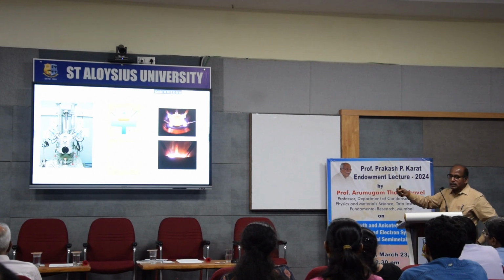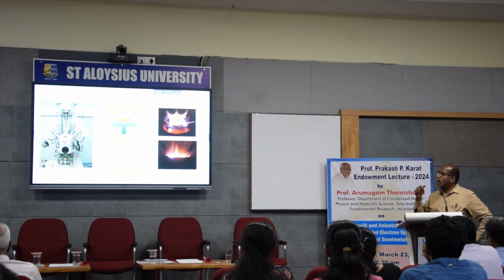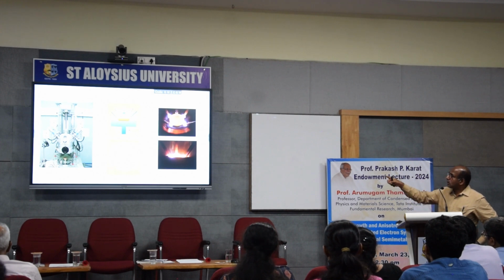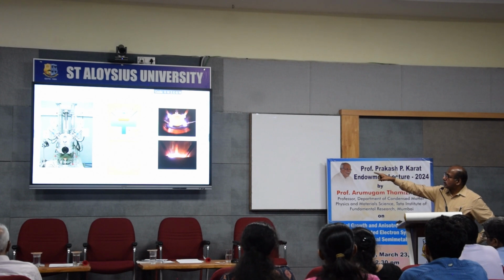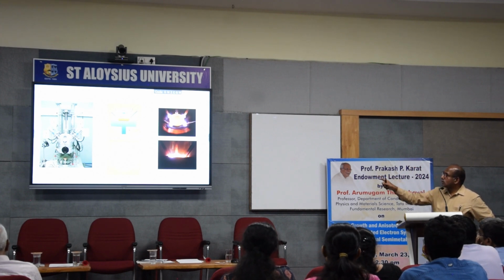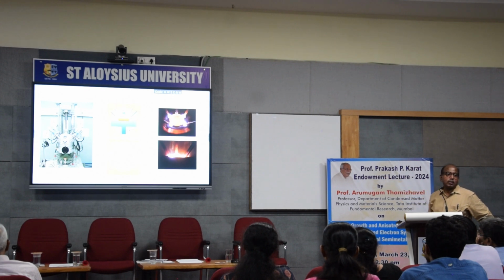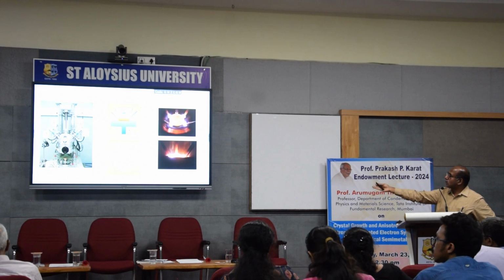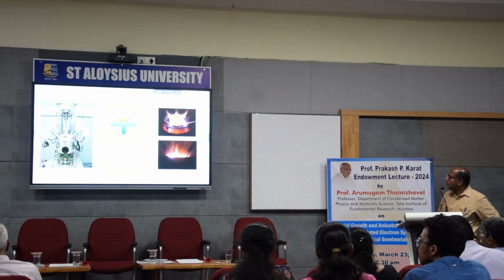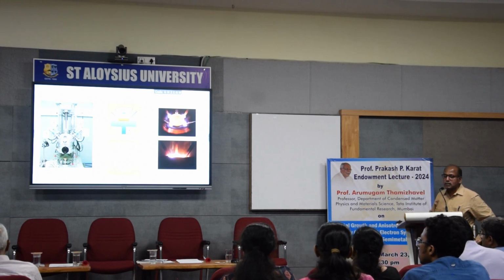When I insert the seed crystal, there will be a local solidification because of the huge gradient. And when there is a local solidification, it will form lots of polycrystals, like the bottom one. The various grains are shown. I do a small necking process so that I allow only one grain to grow into a single crystal. So this is how the crystal growth looks on the right hand side, and you can see that the crystal pulling speed is about 10 to 15 mm per hour.